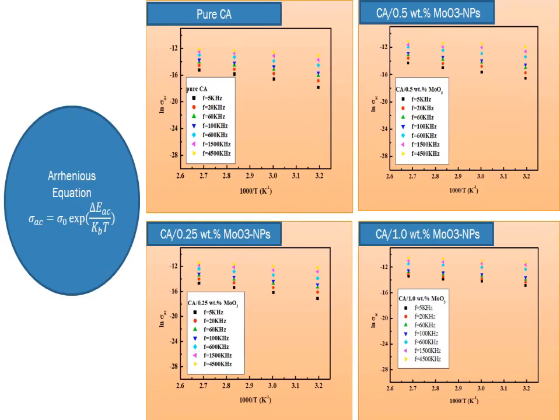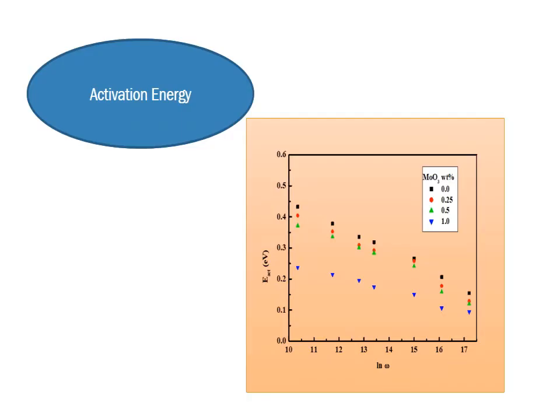According to the Arrhenius equation, we can calculate the activation energy by drawing a relation between ln sigma AC as a function of reciprocal of temperature, and from the slope we can get the activation energy for all the samples. Here the activation energy is drawn as a function of frequency, and we observe that the activation energy decreases with increasing frequency, and this occurs in all our samples, which means that the correlated barrier hopping model is the dominant mechanism for conduction.